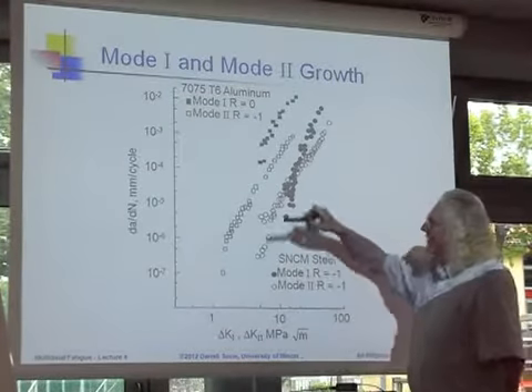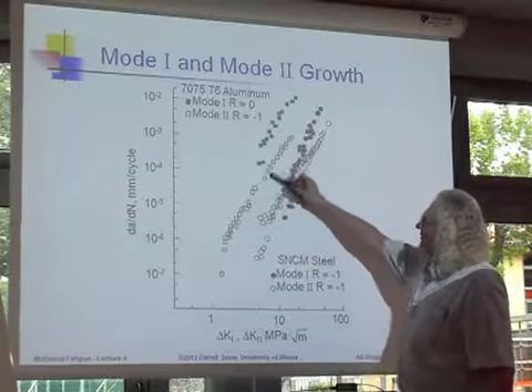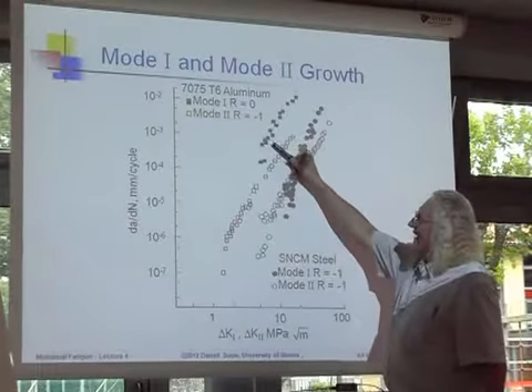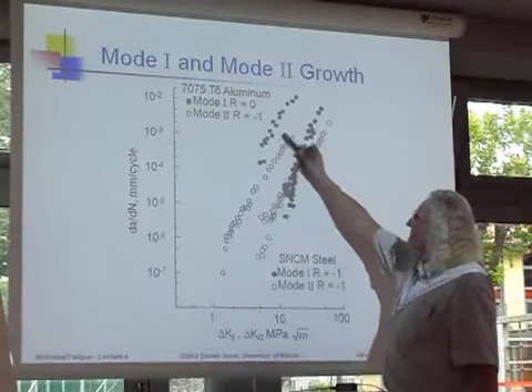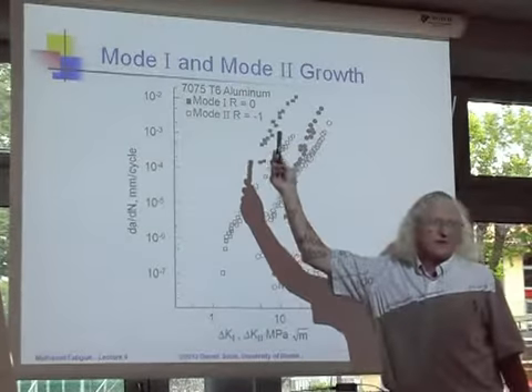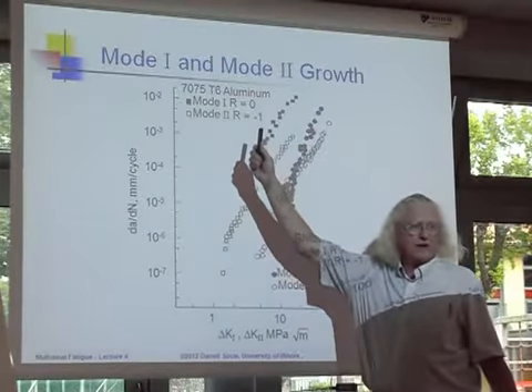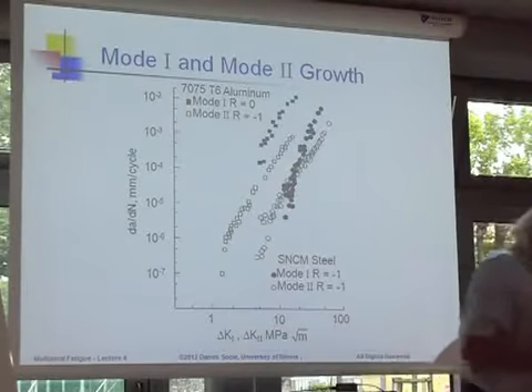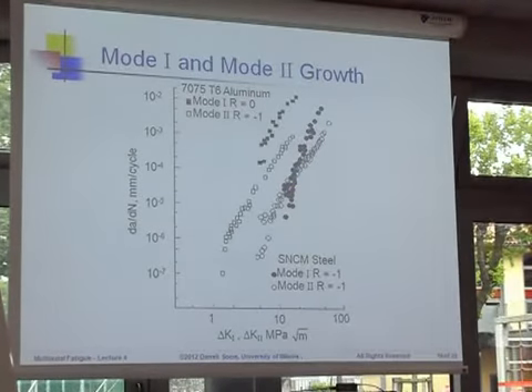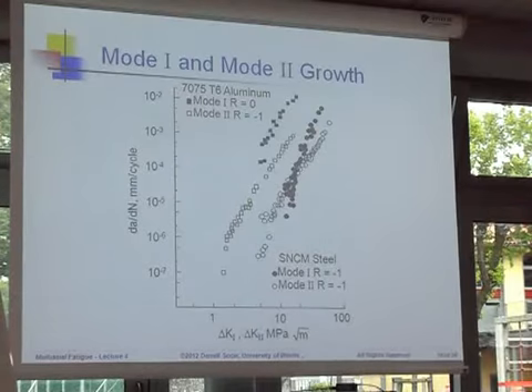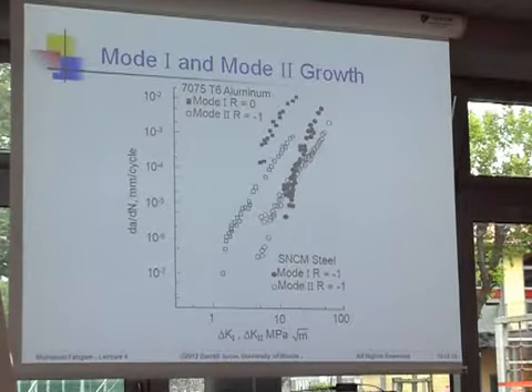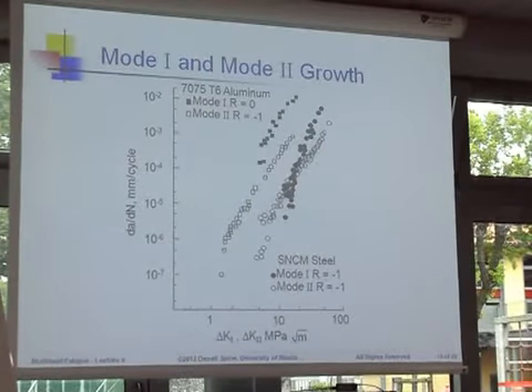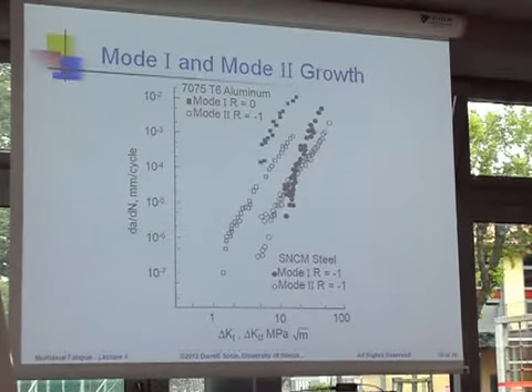And then I find from the same author, I can find that the mode 2 growth rate is actually less than the mode 1 growth rate. And I can find data that shows the mode 2 growth rate is greater than mode 1. And so what I hope I have done in the last few minutes is to paint a very confusing picture, right? Because it is. And the reason is that people haven't done the careful experiments.